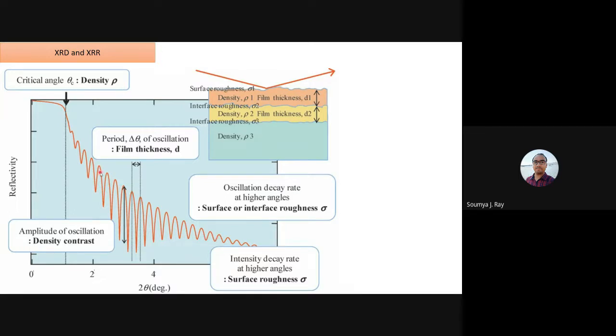And here the sharpness of the oscillations is determined by the interface quality. For example, if the interface is very uniform, then you will have more constructive interference, and as a result the oscillations will be sharper. But if the interface is very rough, then the output intensity will not be as good as that of a very smooth interface. Then you will kill these oscillations, and you might get very rough or average oscillations. So that tells you detailed insight about the interface quality.